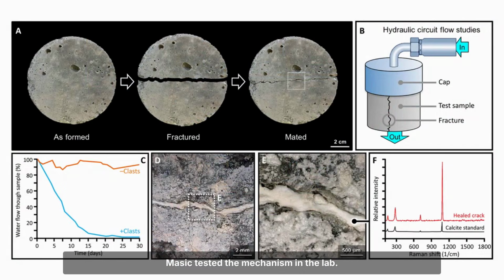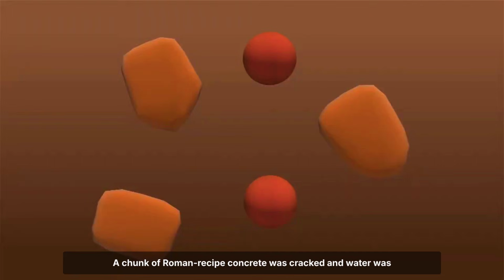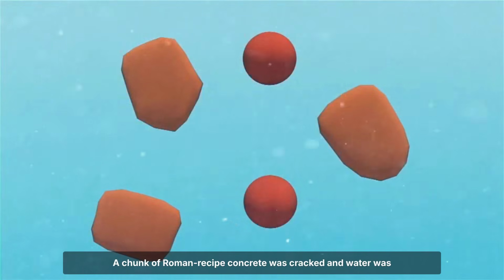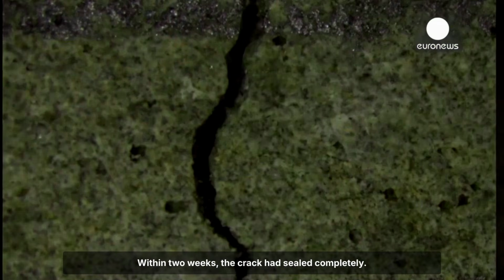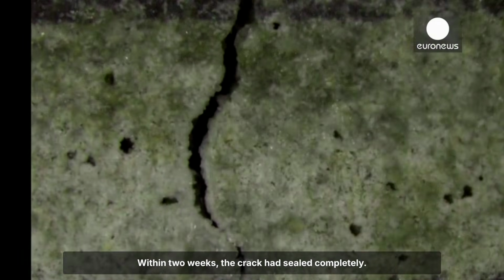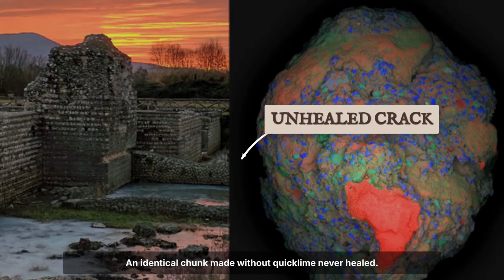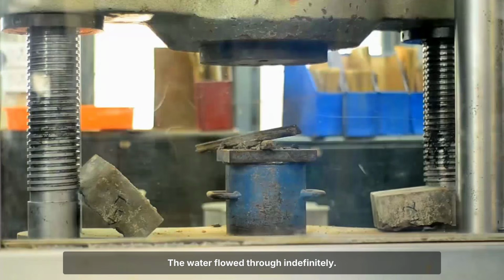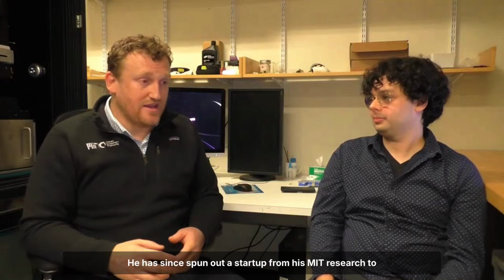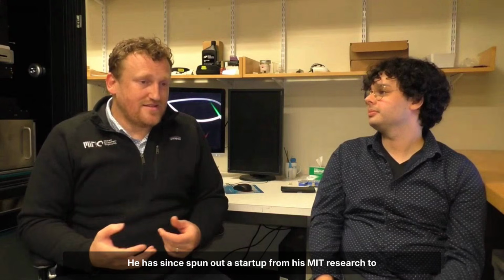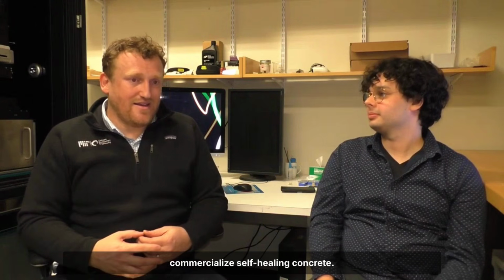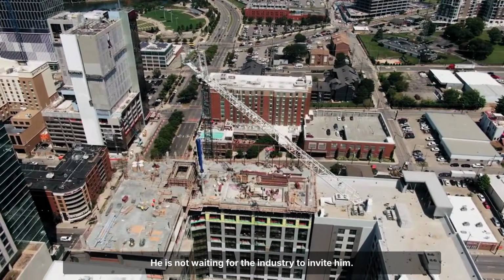Masic tested the mechanism in the lab. A chunk of Roman recipe concrete was cracked and water was introduced. Within 2 weeks, the crack had sealed completely. An identical chunk made without quicklime never healed. The water flowed through indefinitely. He has since spun out a startup from his MIT research to commercialize self-healing concrete. He is not waiting for the industry to invite him.